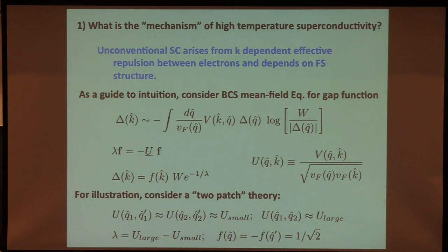The second thing is if you go into an antiferromagnetic ordered state, you rearrange the Fermi surface. You gap out large portions of the Fermi surface and you reduce the density of particles to pair. So antiferromagnetism is for several reasons bad, but a little bit of antiferromagnetism is sort of good.